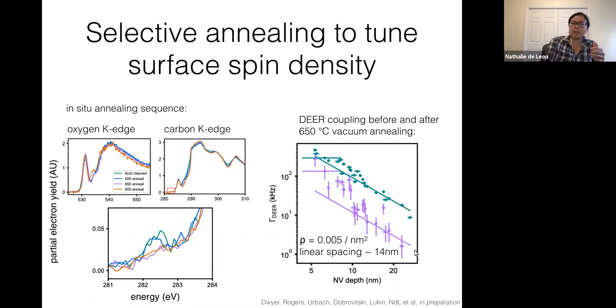So on average, your NV center is actually much closer to the surface spins than the surface spins are to each other, which means that instead of seeing this monotonic increase in DEER coupling as you approach the surface, what you should see is a statistical spread, right? Because you should be sampling some configurations where you accidentally have a surface spin that's very close, but also configurations where you have a surface spin that's very far away. So that's the first statistical puzzle.